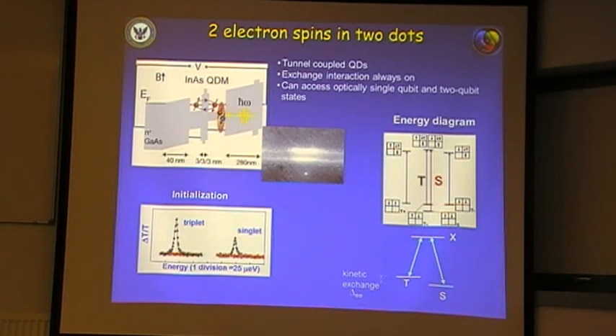This system deals with these so-called quantum dot molecules, which are very popular. We've done a lot of work on them at NRL. It's possible to grow these quantum dots quite close together. What happens here is you grow one quantum dot, which is constrained by strain in the system. The next one grows naturally on top of it, so these are not that difficult to obtain, especially after we've worked on it for a few years.